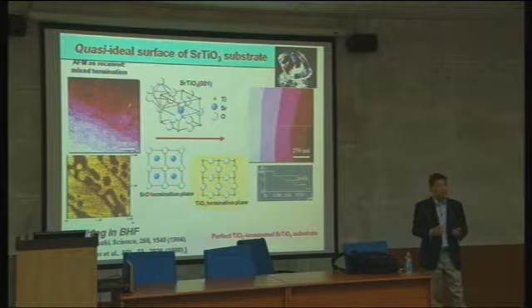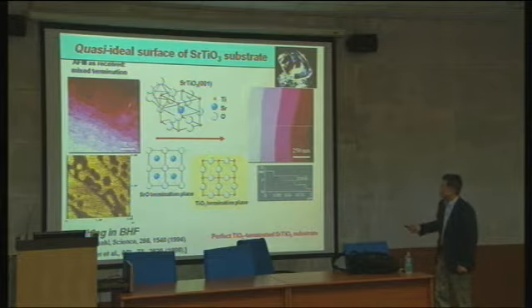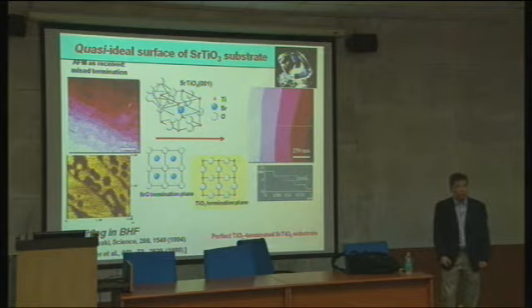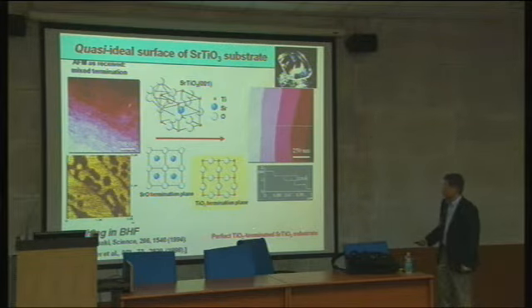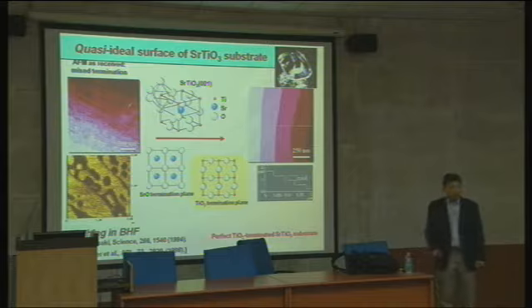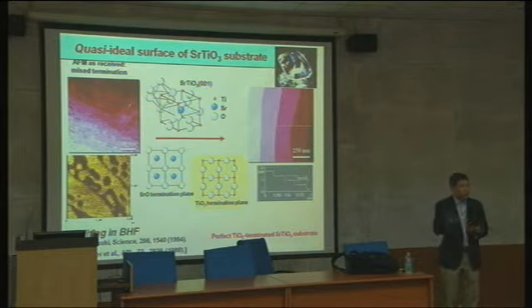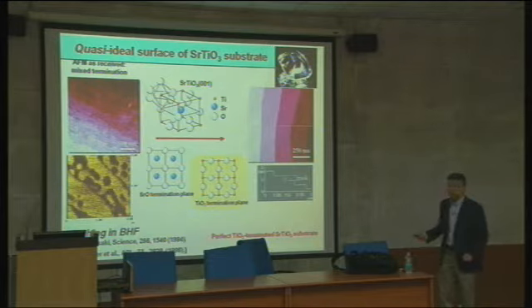So how can you make your films uniform everywhere, with the same kind of quality? How can you do that? That's one of the challenges we have: to make your substrate material a well-defined single termination. Can you make it 100% this termination everywhere on your substrate? This technique was developed by a couple of groups, one a Japanese group, another a Dutch group. And they made a substrate terminated 100% with TiO2 termination.